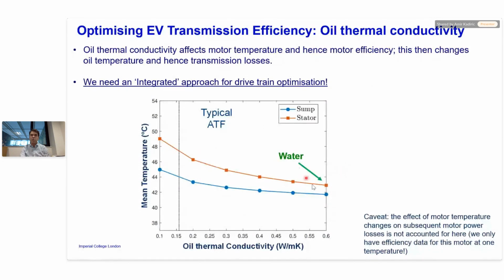So why don't we use a high thermal conductivity, high thermal capacity fluid, such as water? And indeed, there are attempts to do that. Pure water is here, but of course you can't put water in a gearbox, but you could put some water-based lubricant, which will be taking you somewhere in this region, about 0.4 and so on. So water-based lubricants are being researched, including here at Imperial, in terms of the application for EDU. Not as good as oils at lubricating, but much better at cooling. So let's see where that compromise is.